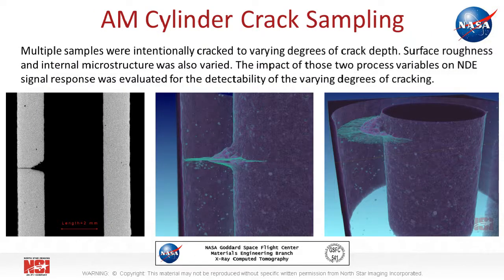This sample was part of a cylinder crack study at NASA where samples were intentionally cracked to varying degrees of depth. The surface roughness and the internal microstructure was also varied with the goal of better understanding the impact of those process changes on the other NDE detectability of the varying degrees of cracking. CT was used to characterize the cracking within the samples. An inverted surface visualization function was performed to display the crack formation in the two images on the right.